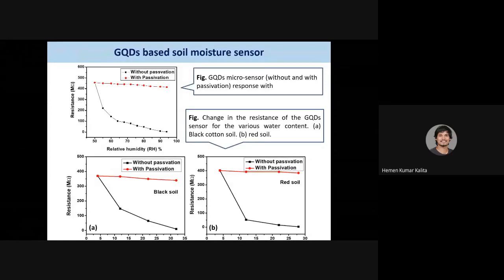So the water content is different; when the water content is more, the gravimetric water content percent is more. Very similar to the humidity, as we increase the gravimetric water content, the resistance is decreasing. We are taking 4 different types of soil moisture. For different soil moisture, we see that as the soil moisture is increasing, the resistance is decreasing. Whereas in the passivation case, even after changing the soil moisture, the resistance is exactly the same. In the case of red soil also, it is showing exactly the same.